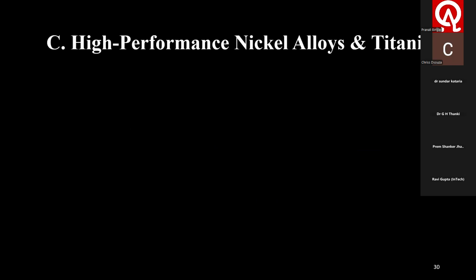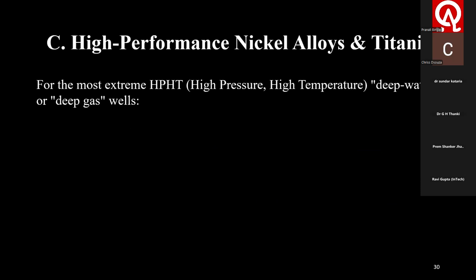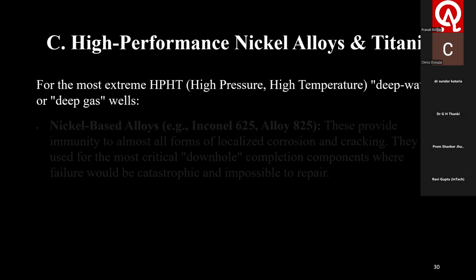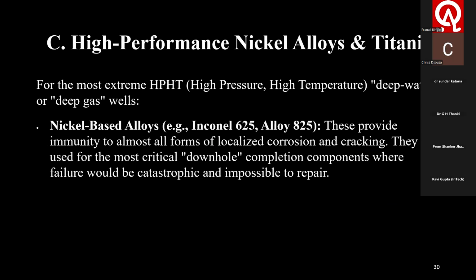Let us go ahead. High performance nickel alloys and titanium. For the most extreme sour service, high pressure, high temperature, deep water, or deep gas wells, here I am talking about Inconel 625 and alloy 825. This provides immunity to almost all forms of localized corrosion and cracking. They are used for the most critical downhole completion components where failure would be catastrophic and impossible to repair.